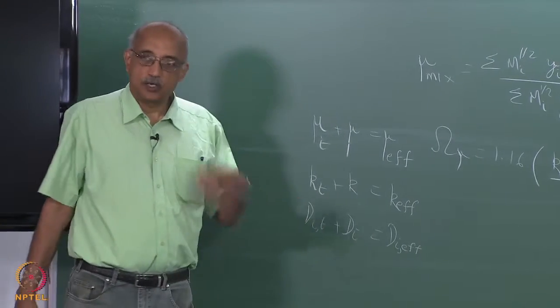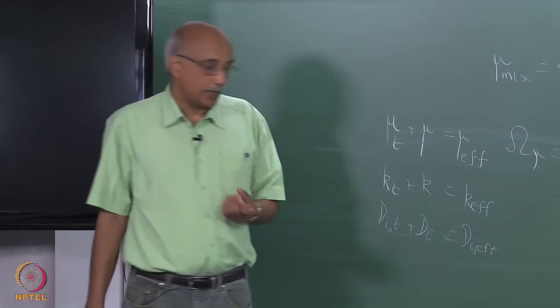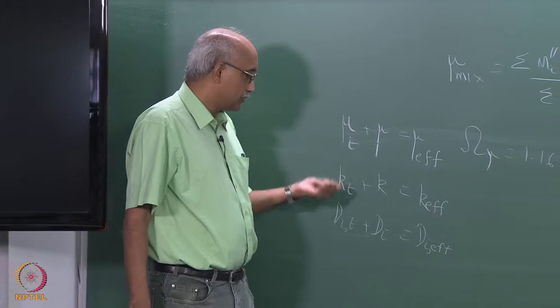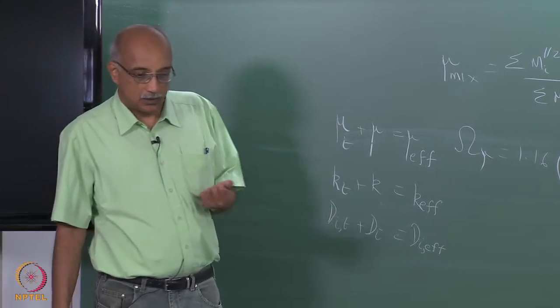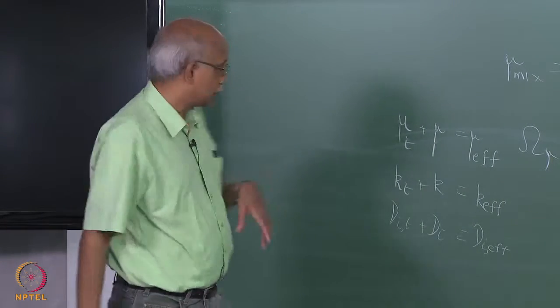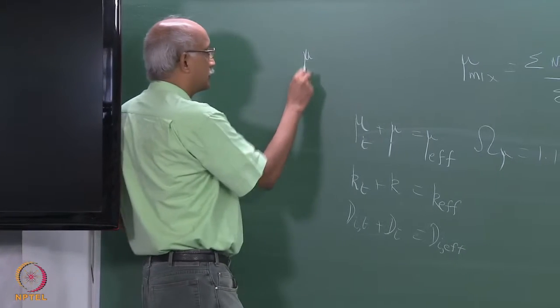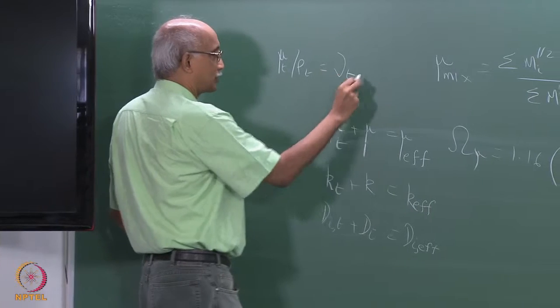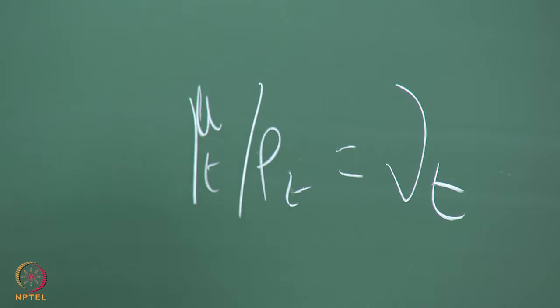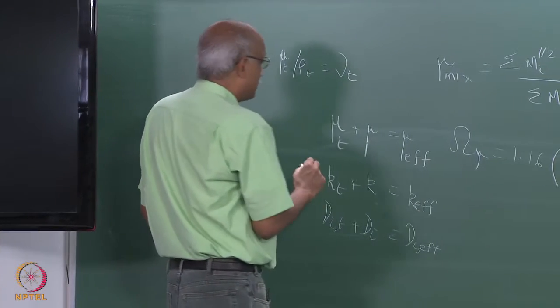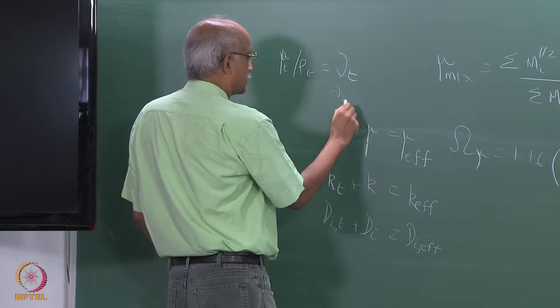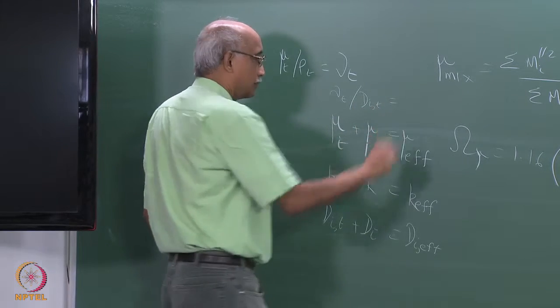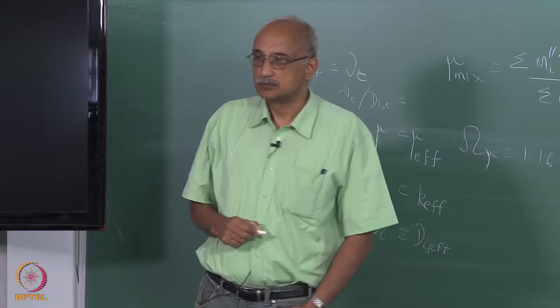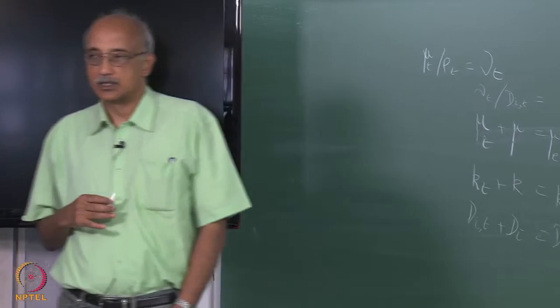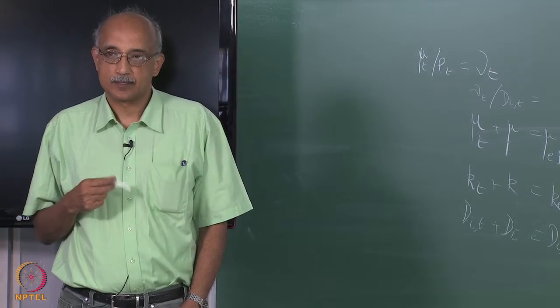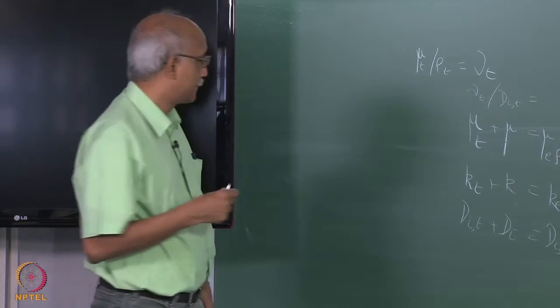Mu T, KT and DiT only depend on the prevailing turbulent conditions, and also interestingly mu T, KT and DiT are very close to each other in terms of the relevant ratios. So, if you take mu T by rho, which is of course the kinematic viscosity nu T, if you take the dynamic viscosity and divide by density, you get the kinematic viscosity. If you take the ratio of nu T to DiT, what do we call that? Nu by D? Any idea? It has a number named after it. Kinematic viscosity divided by diffusivity is called the Schmidt number, ScT.